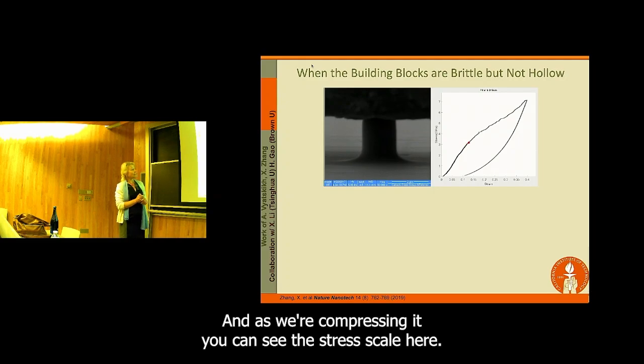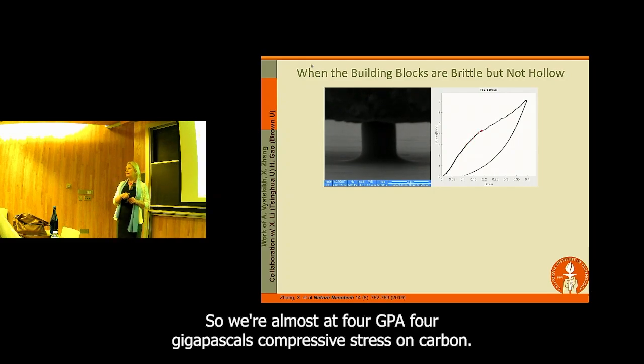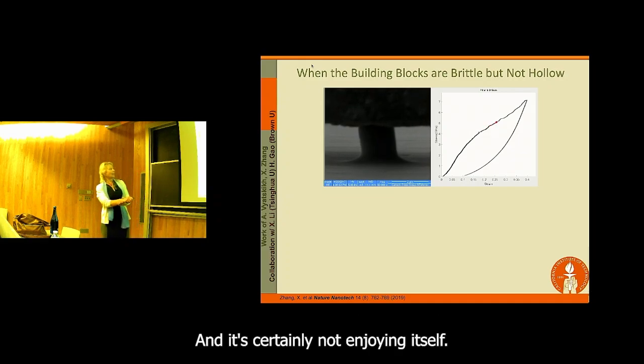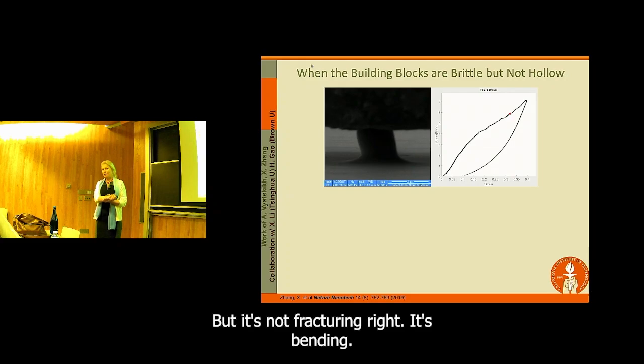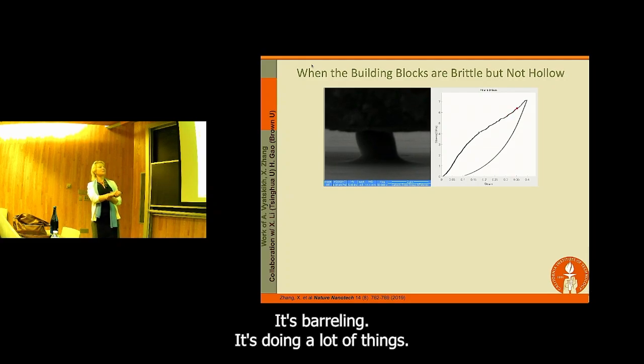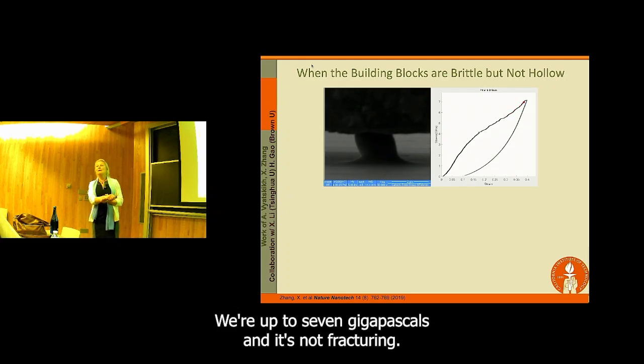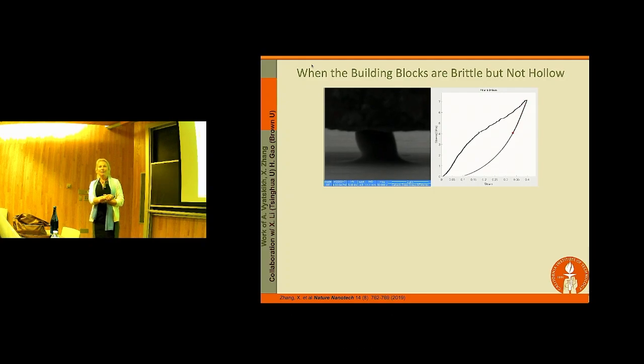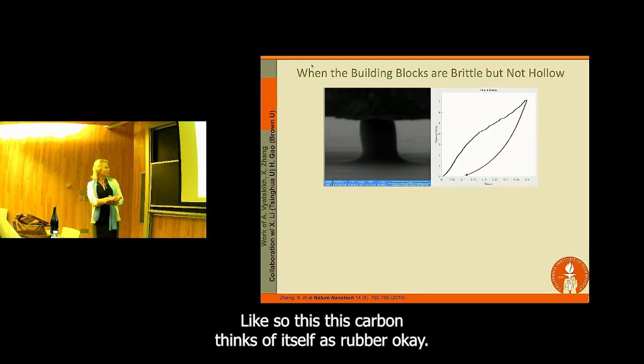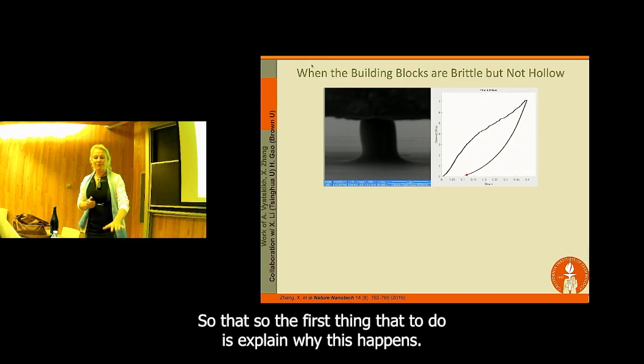As we're compressing it, you can see the stress scale here. We're almost at 4 GPa, 4 gigapascals compressive stress on carbon. It's certainly not enjoying itself, but it's not fracturing, right? It's bending, it's barreling, it's doing a lot of things. We're up to 7 gigapascals, and it's not fracturing. That's unusual, right? This carbon thinks of itself as rubber. So the first thing we had to do was explain why this happens.